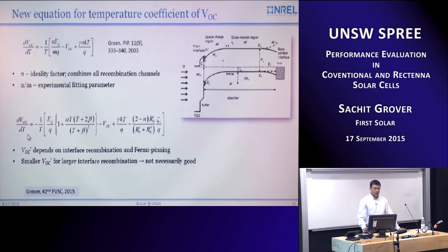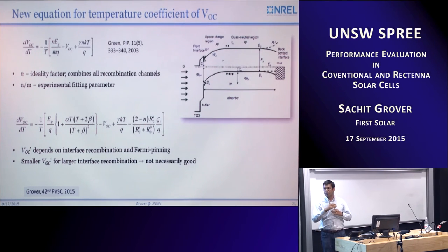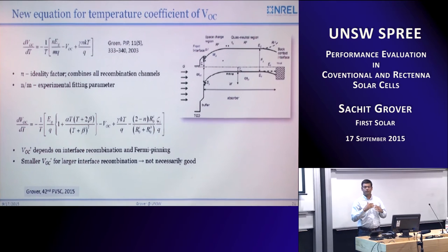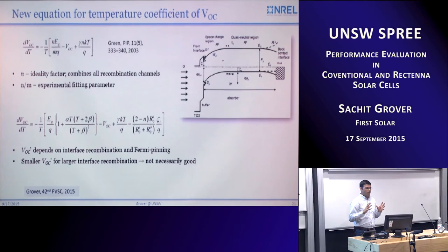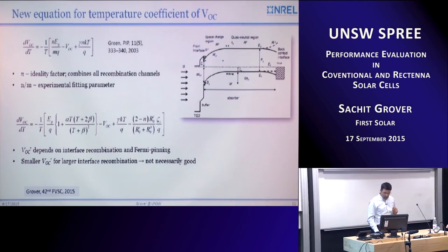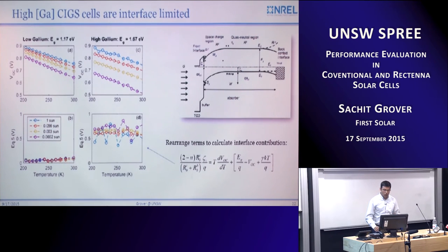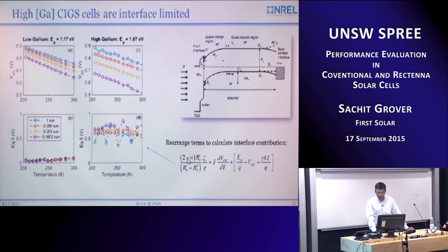reduce the temperature coefficient. So that makes sense, because now the temperature coefficient of the VOC is not purely a function of recombination. It's getting fixed by the Fermi level, by the position of the Fermi level, due to the interface recombination. And that's how it affects. So let me take an example in the next slide and show what it does. And I rearranged the terms to bring out this interface recombination separately.